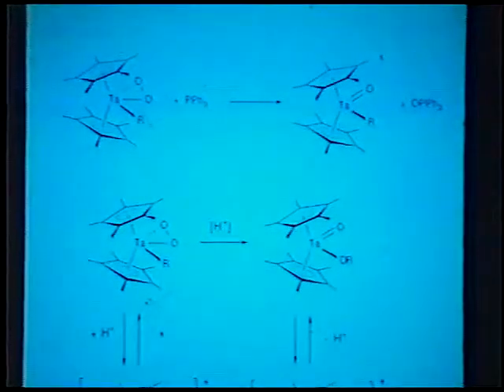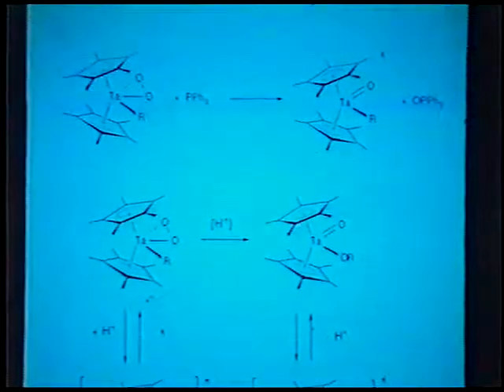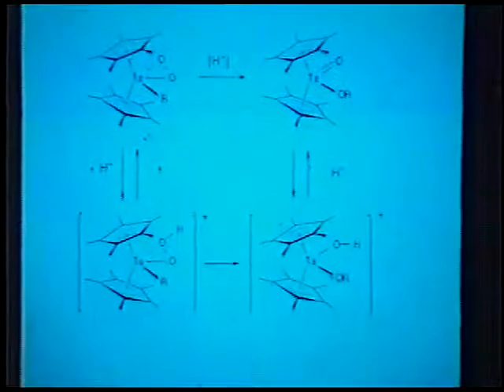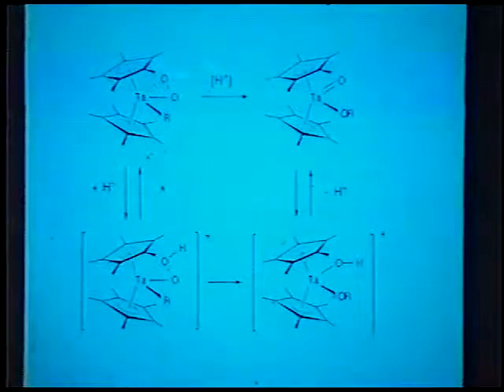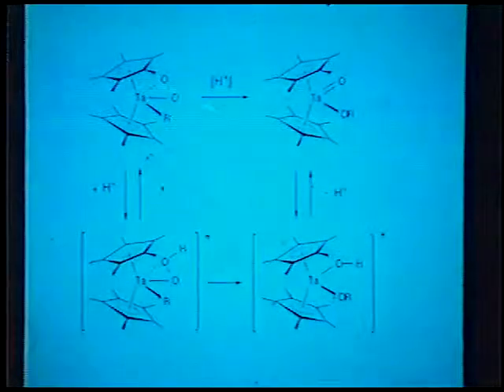And after a while, we traced that observation to the catechol, the tertiary butyl catechol, that they add to styrene to stabilize it against polymerization. Indeed, we purposely add weak acid to show that you can catalyze this carbon-oxygen bond forming reaction that occurs with OO bond cleavage to give this oxo-alkoxo product. Our thinking is that this involves initial protonation of this distal oxygen. That encourages the alkyl migration to the oxygen in the OO bond cleavage, and the resulting hydroxide deprotonates the product.